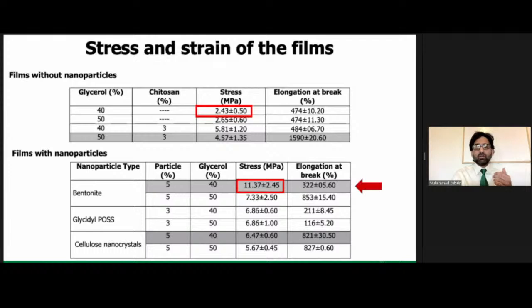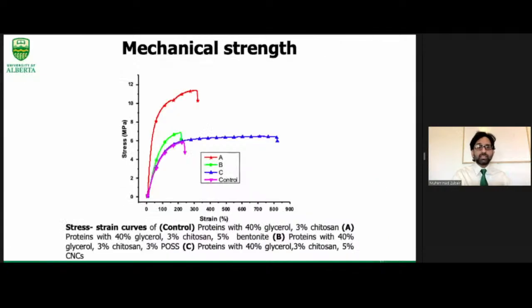From this, we furthermore only characterized the films which have maximum tensile strength, that is bentonite, POSS, and cellulose, with 40% glycerol and bentonite 5%, POSS 3%, and cellulose nanocrystal 5%. So we only characterize the materials with a maximum tensile strength. This is the stress strain curve of the films developed.